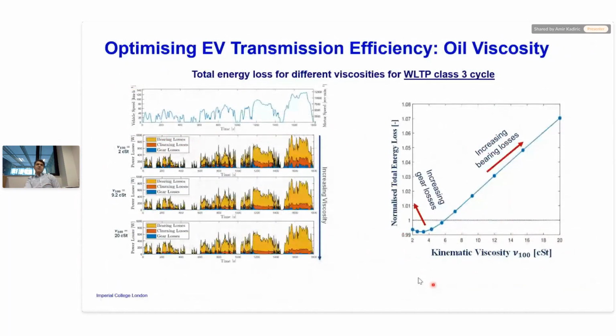What we did then is take a series of hypothetical oils and change the viscosity. So we had lots of different viscosities, and I'm showing you figures here for oils of 2 centistokes, 9.2 centistokes, and 20 centistokes at 100 degrees. And again, we just run it through a WLTP cycle, and I'm showing you the same plots of bearing, churning, and gear losses in yellow, orange, and blue, respectively.